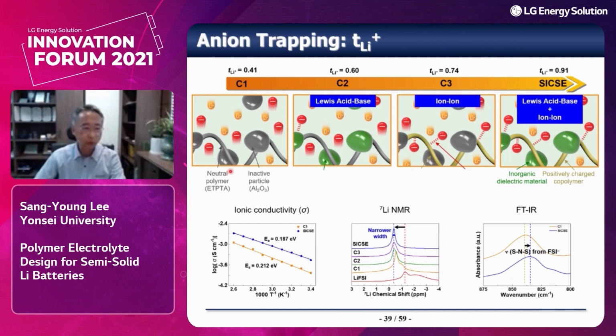As a control sample, we used the conventional neutral polymer network and inactive alumina particles. In that case, the cation transference number is approximately 0.4. When we replace them with inorganic particles containing Lewis acid, we see improvement in the cation transference number, and when we combine the Lewis acid interaction and the ion-ion interaction, we reach a cation transference number that is almost unity, 0.91.